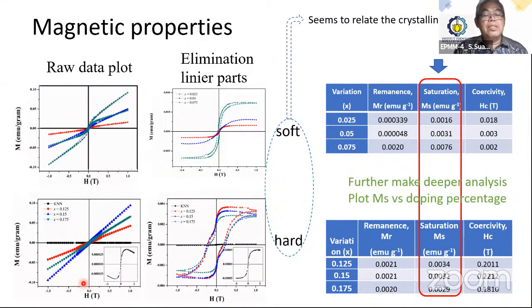The magnetic measurements record magnetizations and applied magnetic fields, H, showing the linear MH curve for the high part and non-linear for the low parts. This means that there is a mixed ferro-paramagnetic in the materials. When the linear part is eliminated, that reveals the ferromagnetic hysteresis curve.